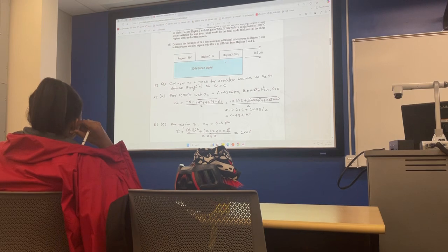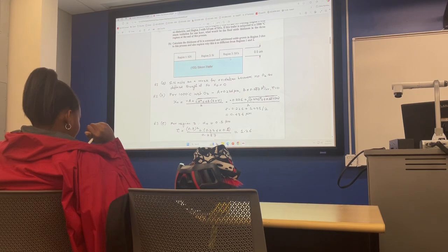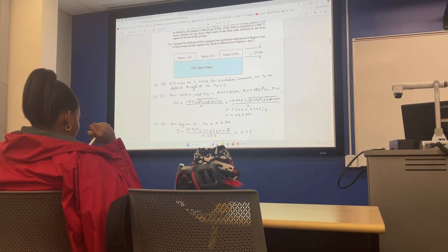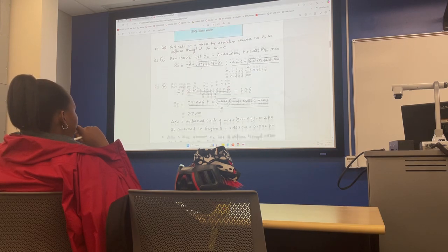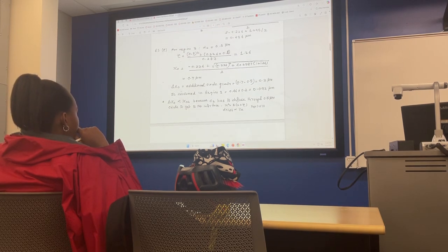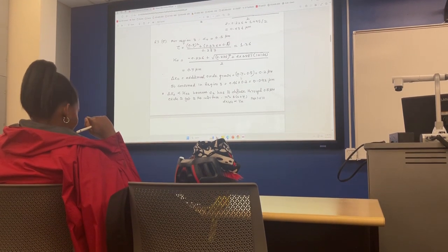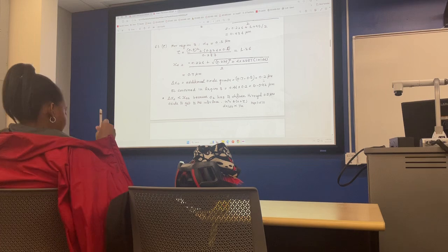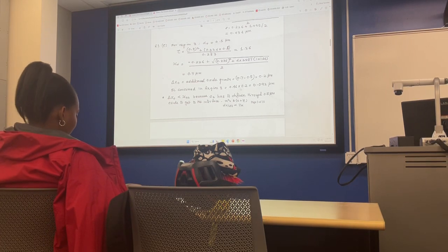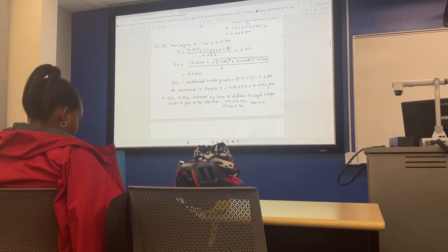So the next question was how much silicon is consumed in this region. So how much extra oxide grew? 0.7 minus 0.5. So 0.46 of that is the silicon consumed here. So the answer to that question was that the additional oxide grown in region 3 is 0.7, which is the final, and 0.5 is the initial. So 0.2 micron is all you grew in region 3. So silicon consumed in region 3 is 0.46 times 0.2, which is 0.092 micron.